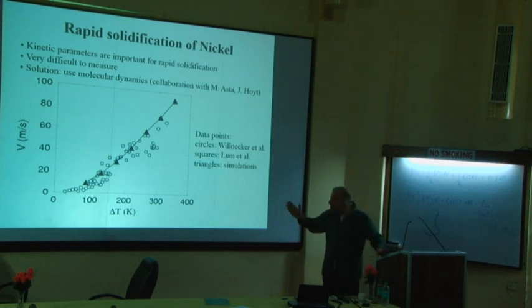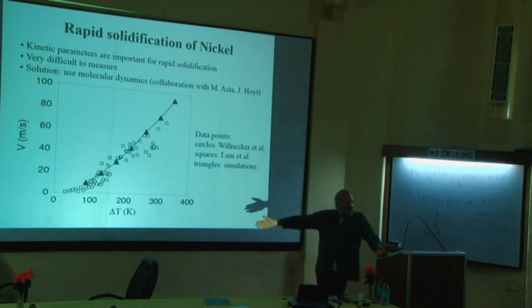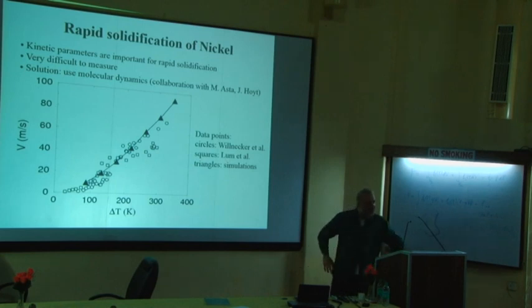Right? So this is a proof that this can work quantitatively if you have the information about the interface properties, that is the surface tension and the interface mobility. There is a quantitative way of fixing the phase field model parameters, and so you can trust what you find. So this is the comparison of this simple data that I announced. So this is the growth speed as a function of the initial temperature of the melt. So we can match this for a concrete substance, which is nickel.